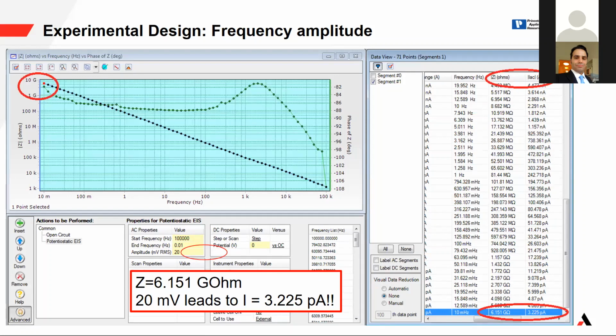If my material is some gigaohm, okay, at 20 millivolts, 6.151 gigaohm generates a current from the instrument of 3.2 picoampere. Picoampere is very small. It's 10 to the minus a lot. So remember, gigaohm generates picoampere. What it means is that if I have a gigaohm, maybe instead of 20 millivolts, I can use 100 millivolts. But then my error can be less.